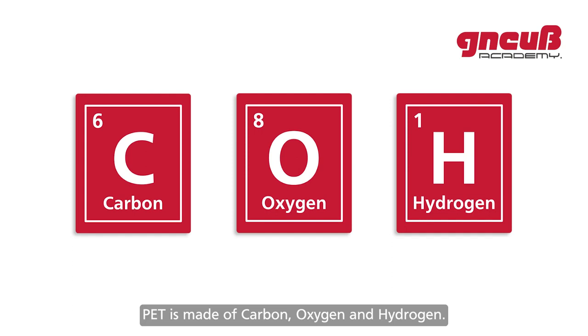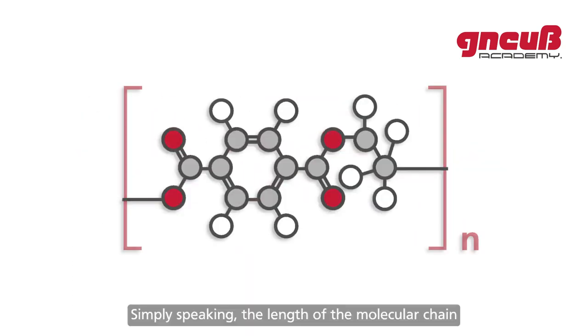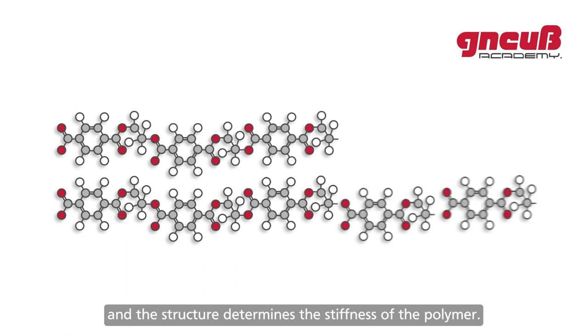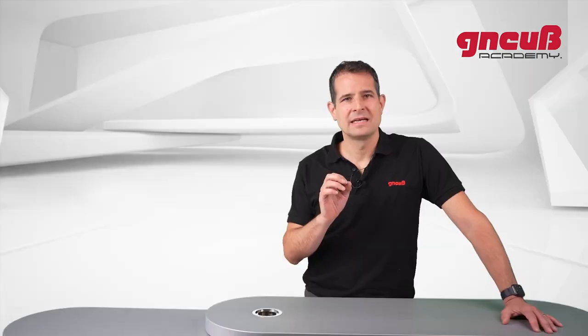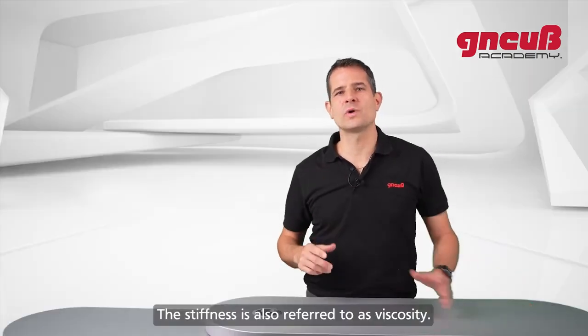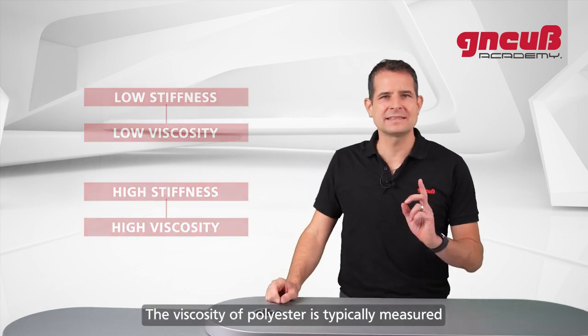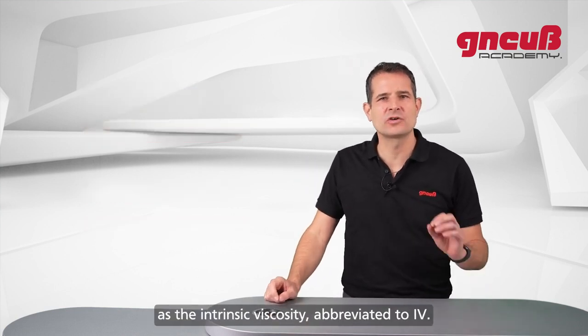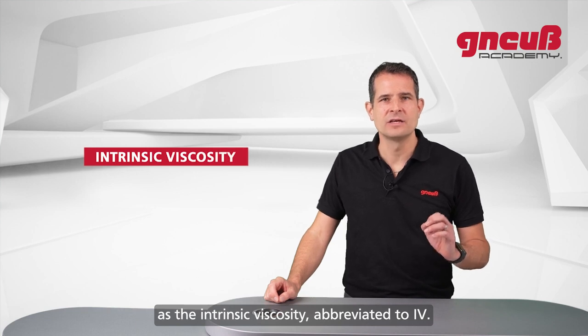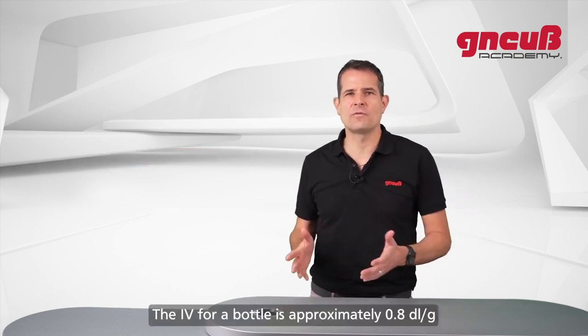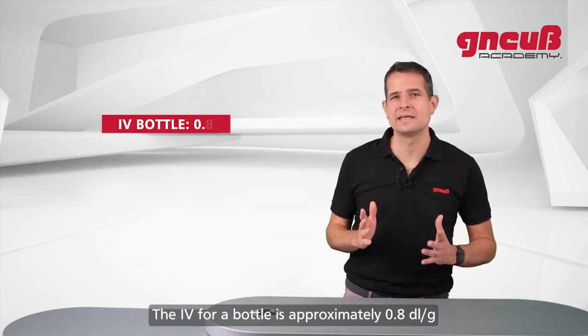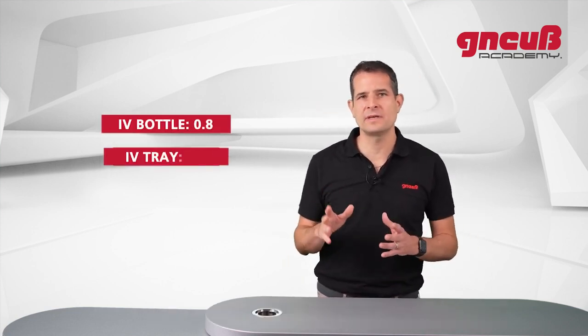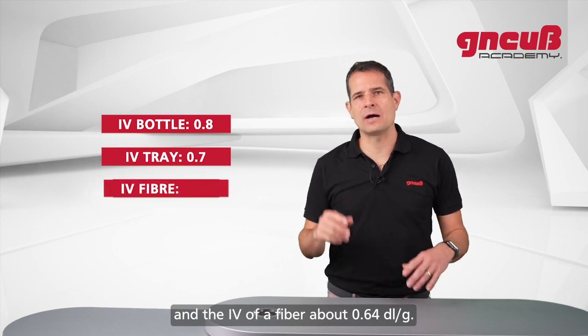PET is made of carbon, oxygen and hydrogen. Simply speaking, the length of the molecular chain and the structure determines the stiffness of the polymer. The stiffness is also referred to as viscosity. Low stiffness, low viscosity, high stiffness, high viscosity. The viscosity of polyester is typically measured as the intrinsic viscosity, abbreviated to IV. The IV of a bottle is approximately 0.8, IV of a tray 0.7, and the IV of a fiber about 0.64.